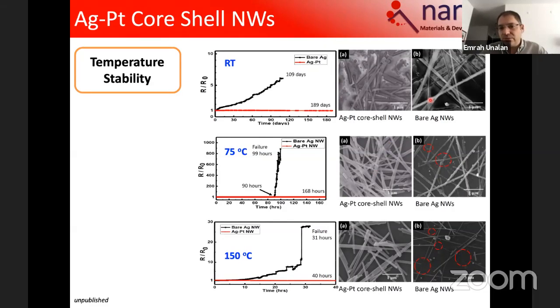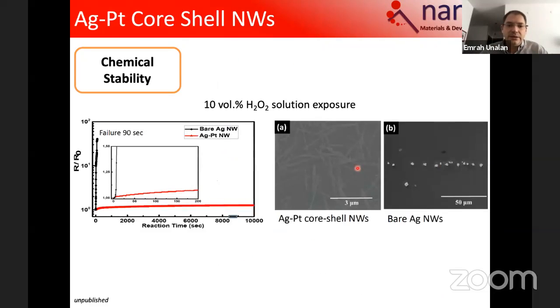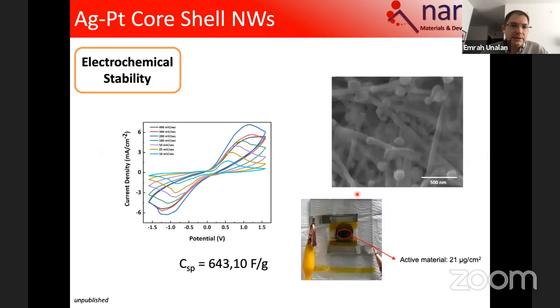And the microscopical images are telling us the same. Our networks in the platinum shell layer, so these are core shell, core silver, shell platinum case, they are highly stable. And one of the other measures that you can quickly see if they are stable is to just drop a solution of hydrogen peroxide, and as you see, failure automatically happens on the bare one, whereas the one with the platinum survives. As you see, the nanowires completely disappear and give you these dots, whereas with the platinum coating layer, network structure stays almost intact.